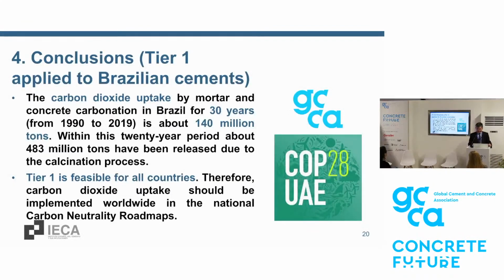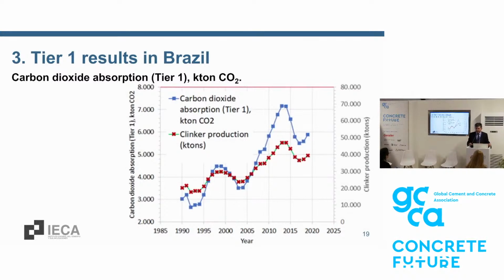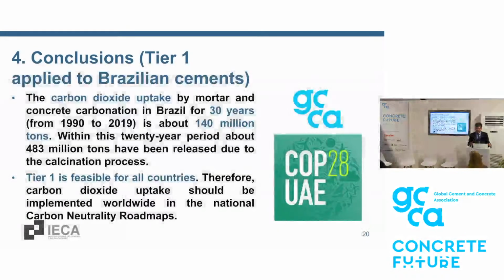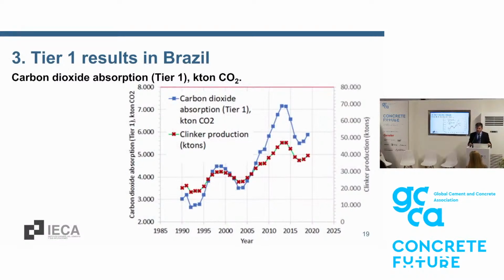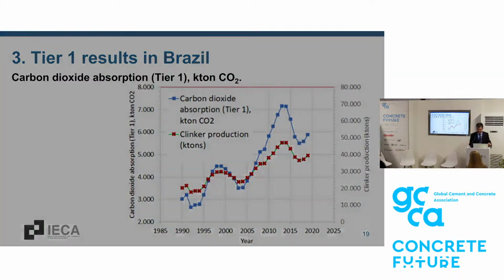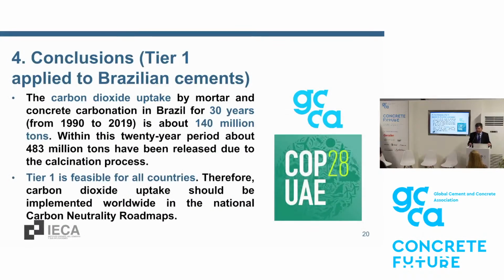Now, the final result and the conclusion is that following the production, the import and the export data, we have the carbon dioxide reached, well, the top was about 7,000 kilotons of carbon dioxide per year. But this is the maximum value reached about 2015. And the conclusion is that the carbon dioxide uptake in Brazil during 30 years, from 1990 to 2019, is about 140 million tons. This is quite a lot, and this is a very conservative method.